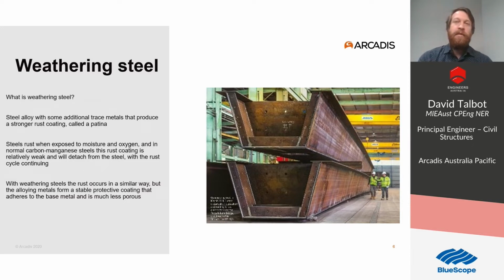Any steel rusts normally when exposed to water and oxygen, but typically that rust coating is quite brittle and porous. Over time that rust forms and then detaches, and then fresh steel is exposed, and the cycle continues on. With weathering steel, it's a similar sort of process, but the patina that forms with those alloys forms a stable protective coating. This coating is a lot stronger, a lot more durable. It adheres to the base metal and it is much less porous. So effectively, it's steel that forms its own paint coating.